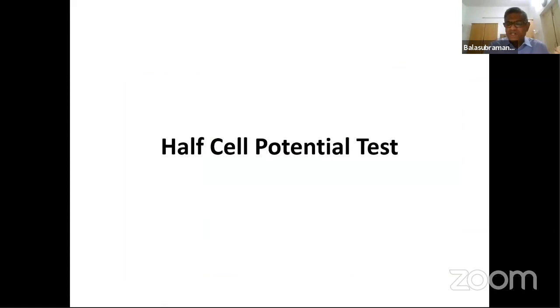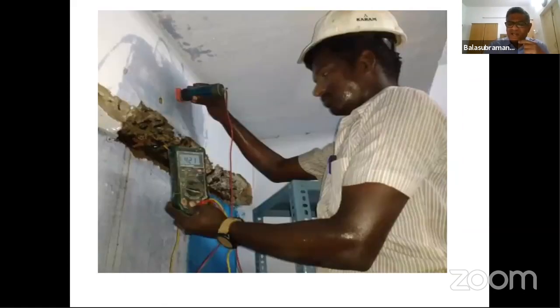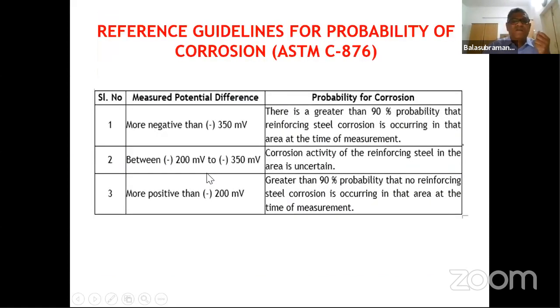And then the half cell potential test is an ASTM test. Most of you would be aware of it. We use a copper sulfate electrode and a multimeter, and one lead is connected to the rod, which is chipped open. Then we measure the potential differences. More negative than minus 350 millivolts means a 90% probability of corrosion. If it is between minus 200 and minus 350, then corrosion activity in the area is uncertain. If it is more positive than minus 200 millivolts, there is a 90% probability that no steel corrosion is happening.